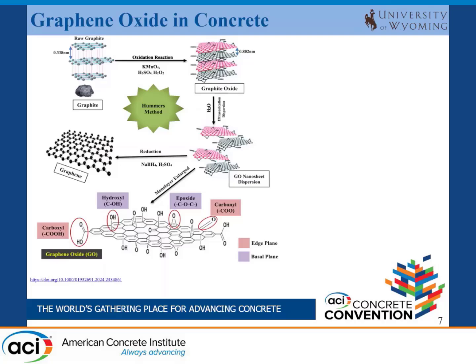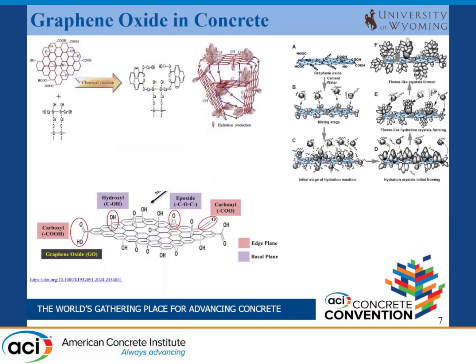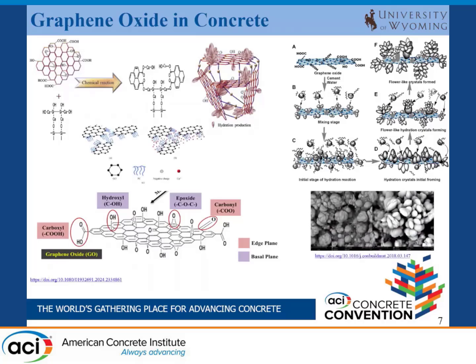If we see the structure of graphene oxide, on the surface there are lots of functional groups present, like carboxyl, hydroxyl, epoxide, and carbonyl. There are some hypotheses that these groups help to react with the cement and make some flower-like crystals on the surface of the graphene oxide, which may help to create a denser structure in the concrete.